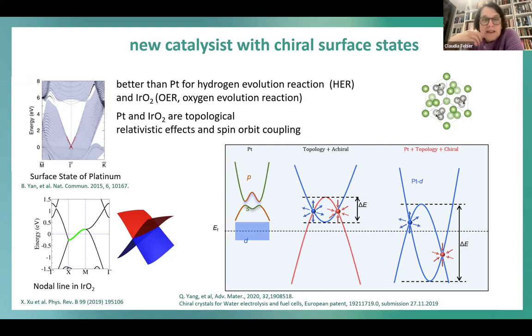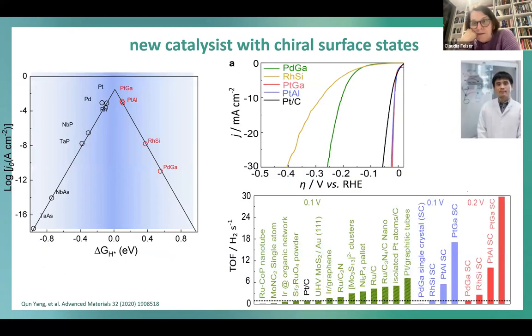So we then really measured their catalytic activities, and this is on the next slide. So you see, they are really the chiral ones. The chiral materials show very, very good performance, as you see here in the volcano plot. At the same time, there are a lot of measurements in this paper. It also shows, depending on the voltage overpotential, that they are performing even better than commercial platinum catalysts. So you can compare it, but anyway, it shows.